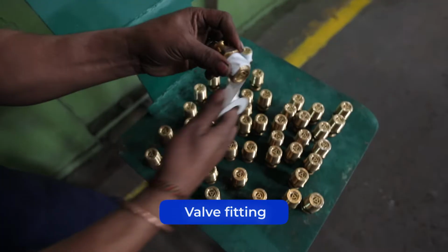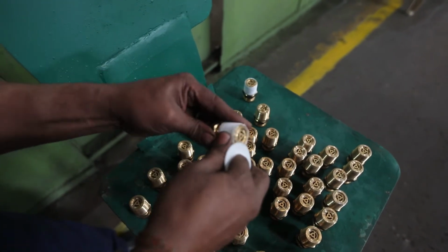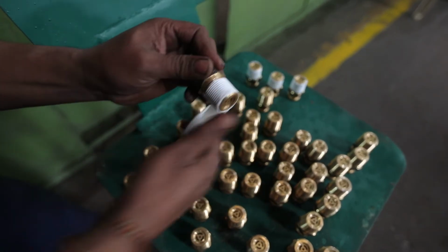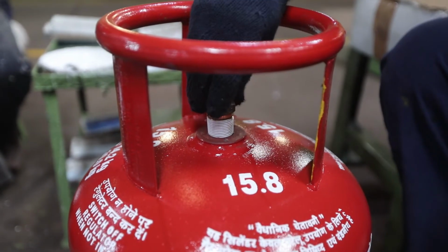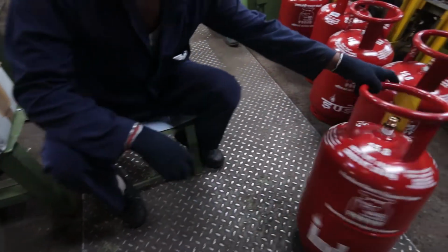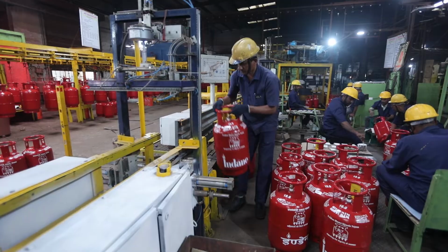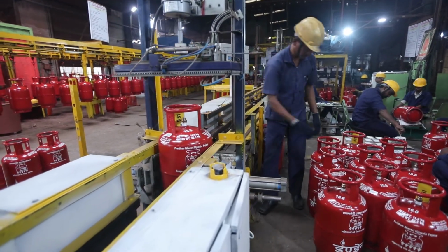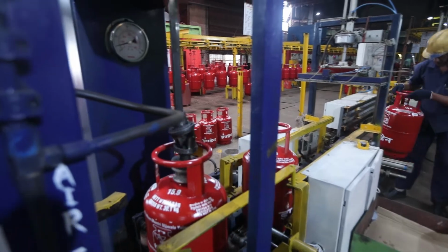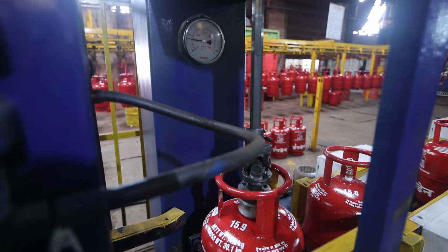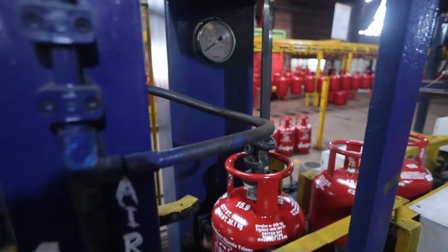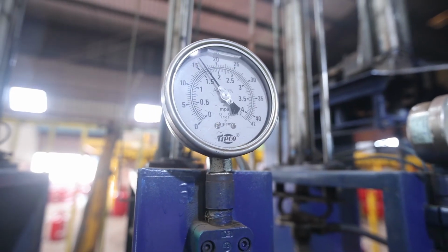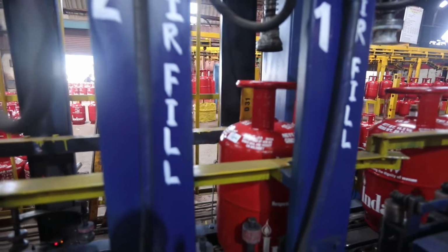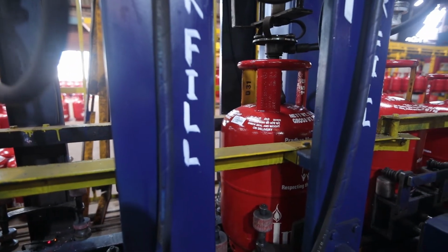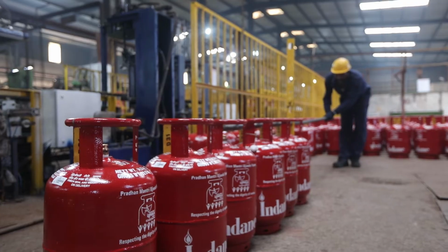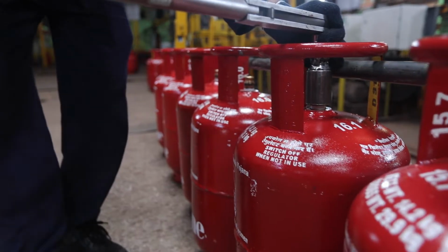SC valves are kept in secured place and custody. Valve threads duly wrapped with 2 to 3 rounds of Teflon tape of 3 to 4 inch width and 40 microns thickness are then hand tightened in the bung of the cylinder. Such cylinders are taken for SC valve tightening on auto hydro torque tightening machine with preset torque value of 145 plus minus 15 pound-feet. The torque exerting spindle stops automatically after attaining specified torque. The torque can be later measured by a duly calibrated torque wrench.